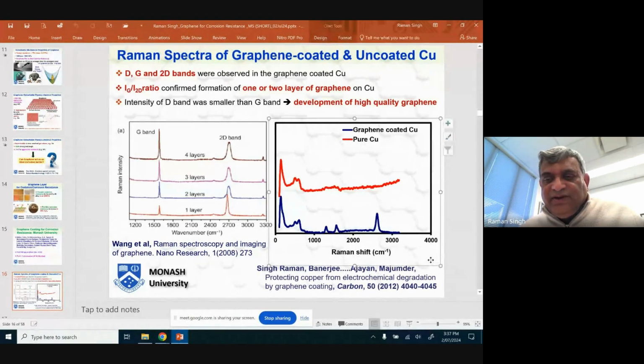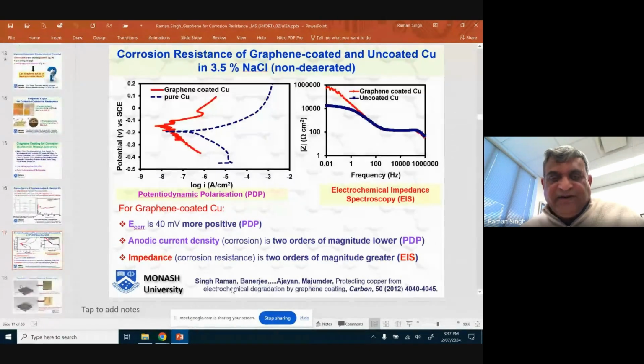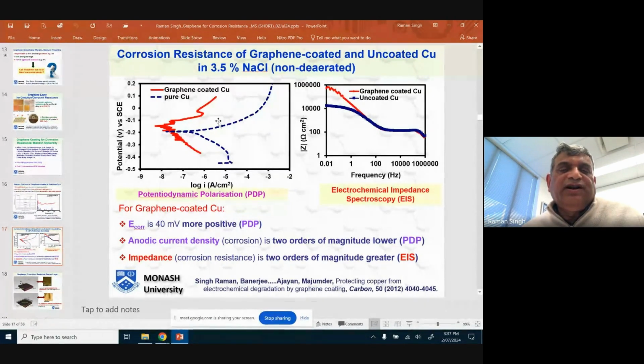So with that, we started to work on corrosion experiments, and you can see once again the same plot that I showed you earlier. The intercept of the cathodic and anodic arms of this potentiodynamic polarization plot gives me the corrosion rate. So graphene coated copper corroded at a rate which was 2 orders of magnitude smaller compared to the pure copper. I repeat, one single atomic layer thick graphene improving corrosion resistance of copper by 2 orders of magnitude. It's a log plot, in a sodium chloride solution similar to seawater.